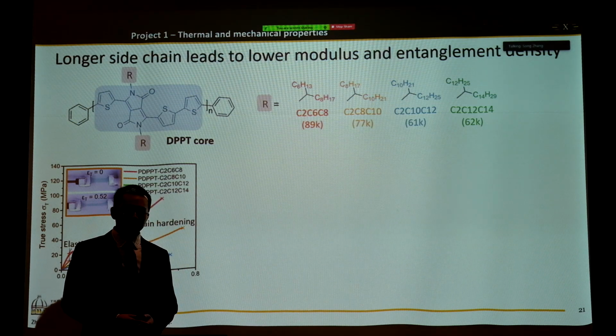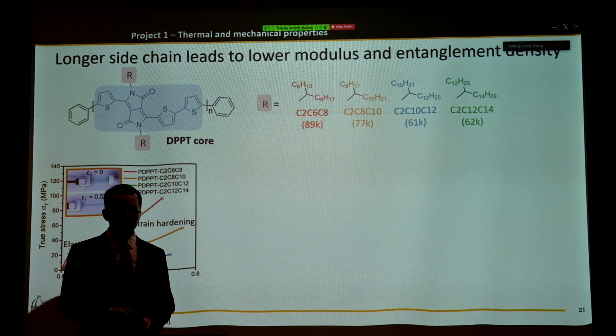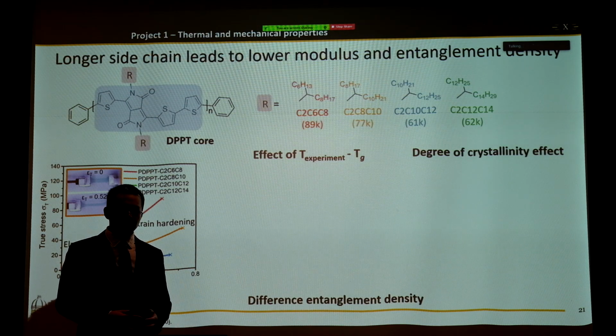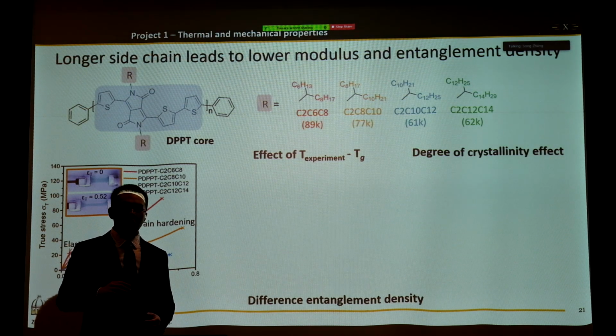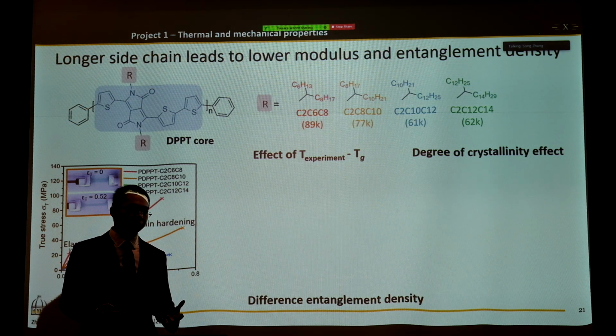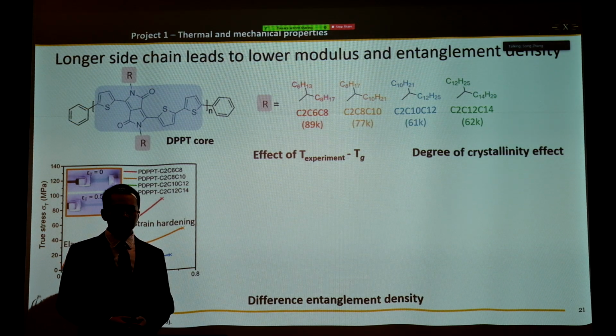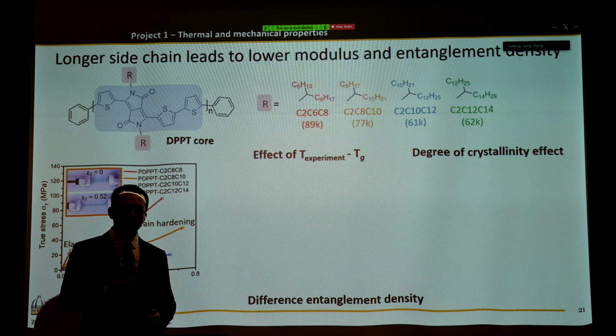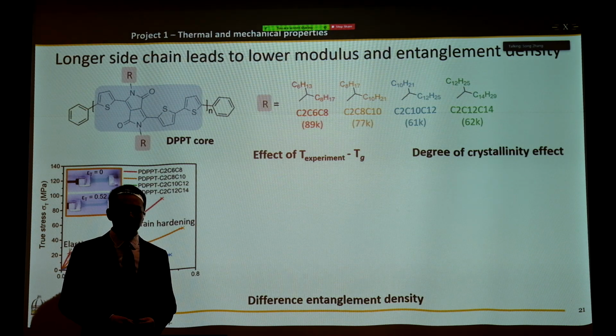Okay, how do we understand this? We have three hypotheses. The first one is that different polymers have different Tg, while our experimental temperature was fixed at room temperature. So it might just be a T minus Tg effect. The second one is the degree of crystallinity effect, since they are different for different polymers. And the third hypothesis is different entanglement density.